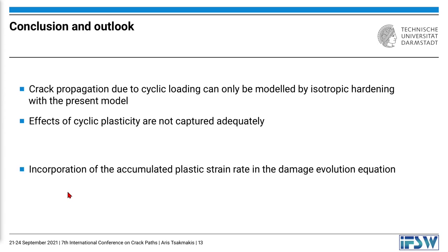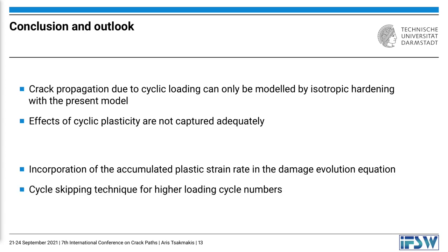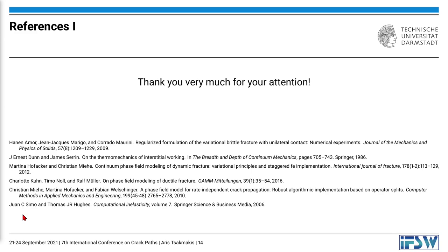To overcome the shortcomings of the present model, one possible solution is to incorporate the accumulated plastic strain rate in the damage evolution equation so that plastic deformation is always accompanied by damage evolution. A second topic for future work is to include a cycle skipping technique in the material model so that higher numbers of loading cycles can be calculated. Thank you very much for your attention.